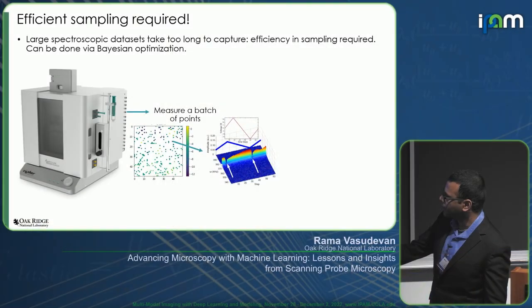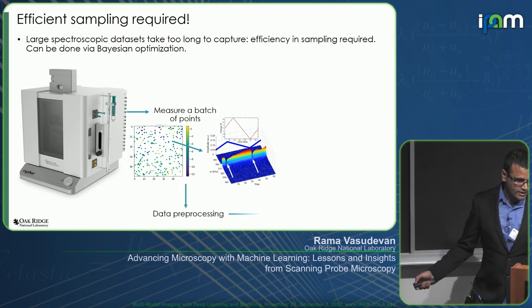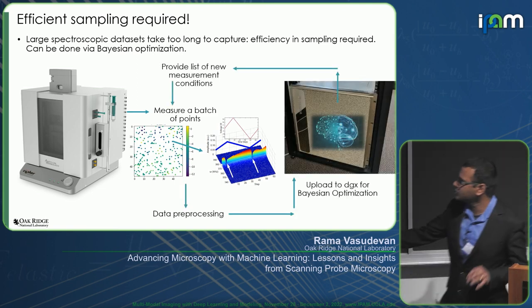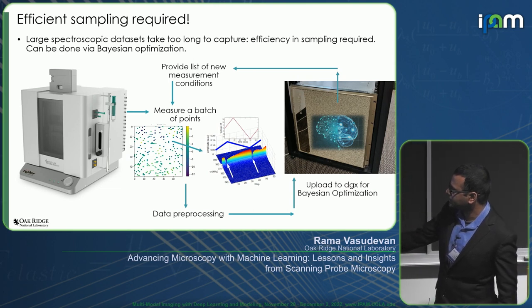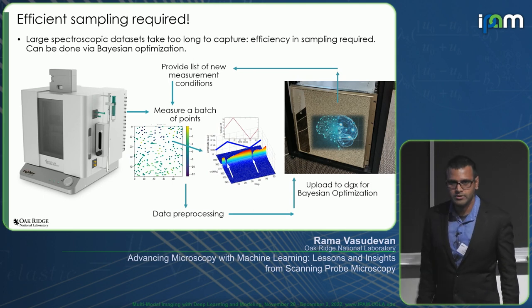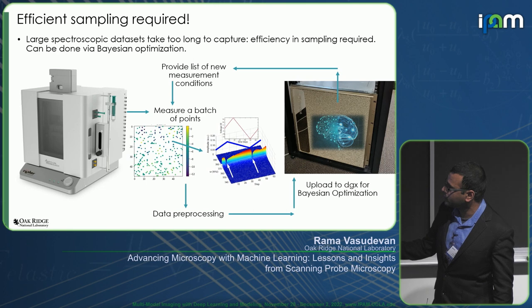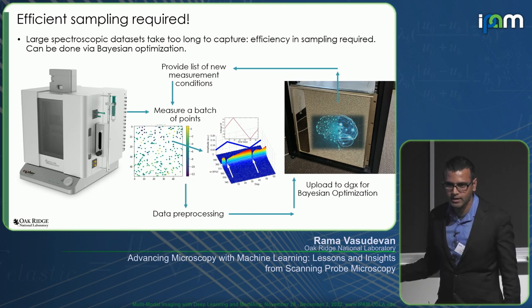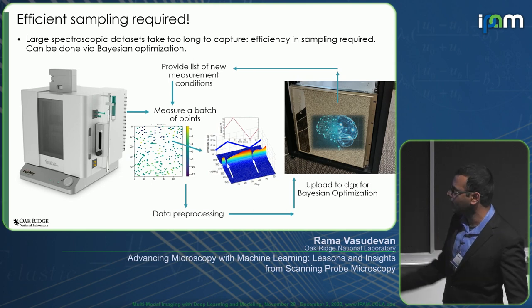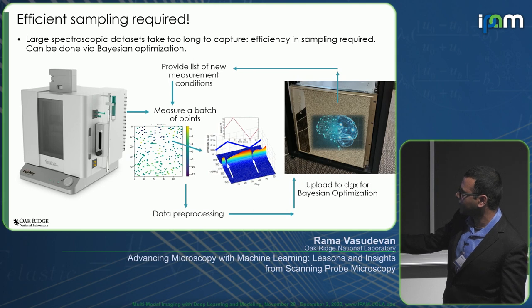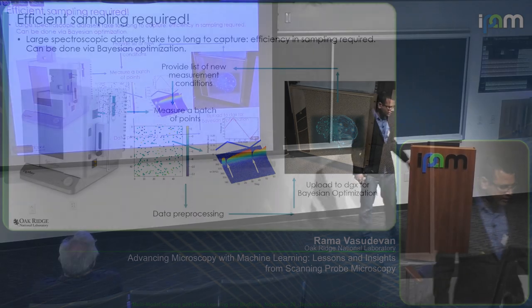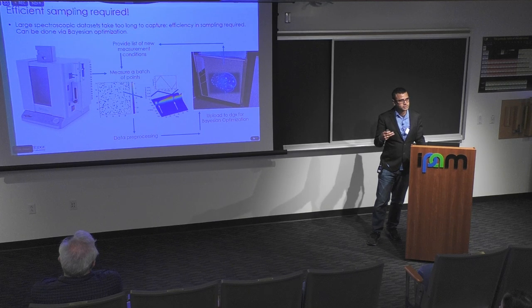One way to do this is, for example, to take a spectrum at random positions. Instead of taking a spectrum at every individual location, I collect spectra at random positions, and then I upload the spectra to some GPU server where we can run algorithms such as Bayesian optimization to optimize the next measurement conditions. In other words, I want to optimize for some target property, like maximizing the area in my spectra. The algorithm then gives me a list of new measurement conditions, which will run on the microscope so that we do not have to scan and collect spectra across a dense array.